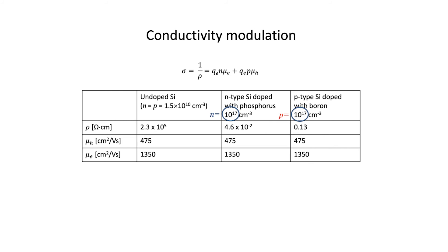Now, 10 to the 17th power, that might sound like a lot, but we're only replacing one in every 10,000 silicon atoms with phosphorus or boron. So we're not replacing very many of these atoms. The only thing that's going to change is that we now have more conduction electrons, in the case of the phosphorus doping, or valence holes in the case of the boron doping. Silicon without the phosphorus atoms had a resistivity 10 to the power of 5 ohm centimeters. But when I added only 10 to the power 17 phosphorus atoms to the crystal, the resistivity dropped down. In other words, I've changed the conductivity of the silicon by seven orders of magnitude by just adding a tiny quantity of phosphorus. So that's the power of semiconductors.